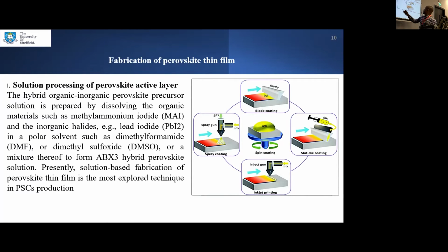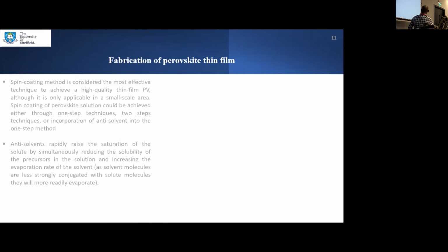We have spray coating, we have spin coating, and we have inkjet printing, and we have slot-die coating. But most of the time in laboratory fabrication, we use spin coating to fabricate perovskite solar cell. And why do we use spin coating? Actually, because it's the easiest and fastest way of producing perovskite in a very short period of time. So how do we spin coat perovskite using a spin coating machine?